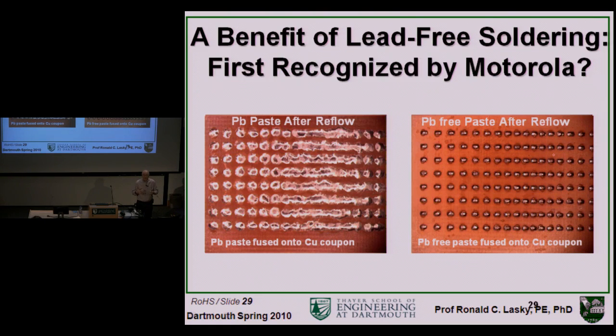Now, admittedly, there are good things and bad things. It's harder to make it wet, so in some cases you might have a solder joint that doesn't wet quite as well as you'd like. You're not getting as much wetting. But this enabled closer lead spacings, and if you ask people that make miniature electronics today, they would tell you they couldn't go back to leaded solder. They couldn't make the product in as small a size as we have today. And this is still not widely recognized.